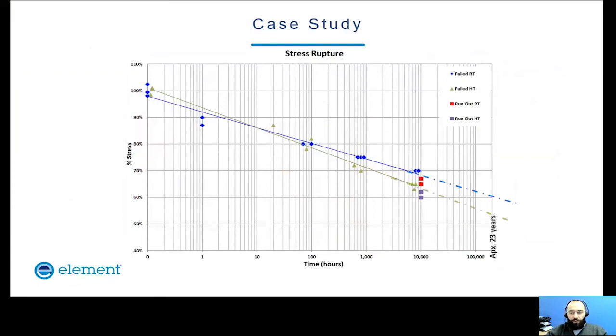Then the graphs can be extrapolated to provide an understanding of the load at the service life of the pipe. In this case, graphs were extrapolated up to 200,000 hours, which is approximately 23 years. Below, you've got 2 levels of stress, one for the room temperature test data and one for the high temperature test data. The stress levels below these, for the required lifetime in the graph, can be defined and used in the design process to ensure that the pipeline will stay in service for its actual service life.